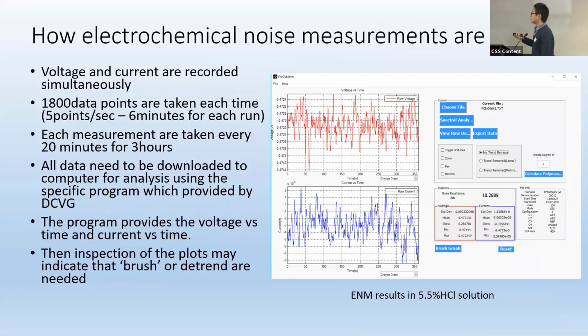As I said, all the voltage and current signals are recorded at the same time during the experiment. In this particular experiment, I have used 1800 data points, and you can set how many points per second. Here it is 5 points per second, and each run takes 6 minutes. The whole set of this experiment takes 3 hours, which is 10 runs for each specimen.